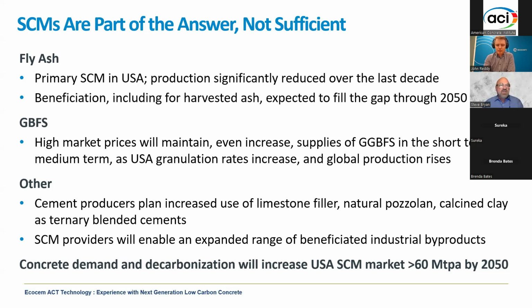All in all, if you look out to 2050, which sounds like a long way away but is really just 25 years away, with the increased demand for concrete as well as the demand to decarbonize, we see that the SCM market will grow by more than 60 million tons in the next 25 years. And that's a very conservative number. If we're able to get the clinker factor down lower, it could be 50% more than that. So that's a very significant amount. What you're talking about is 60 to 90 million tons, which is roughly equivalent to today's current production of OPC.